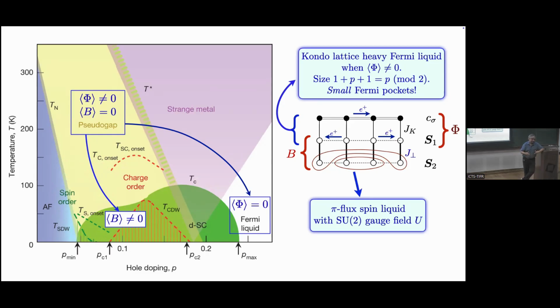So in fact you get a D wave superconductor, not any other wave, and that the nodal points have certain properties is very much linked to the spin liquid. It won't work with any other spin liquid. Well, may work with some others, but this one seems to be the simplest thing to try, and then it works.